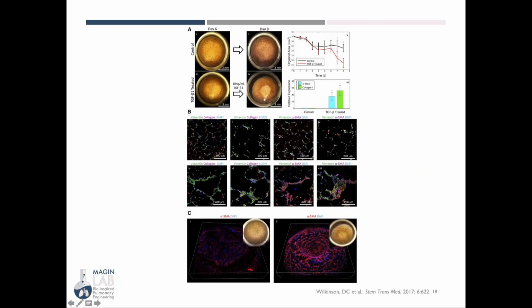So you can see here, you're starting to see the structure of lung tissue. They've stained vimentin, or the fibroblasts, in green here, collagen 1 in that magenta color, and then of course DAPI is blue. And so using these alginate beads, they've created the geometry that we're expecting to see in lung, and they've done this in a 3-dimensional way. They went on to study how these cells can be activated by exposing them to TGF-beta, one of the growth factors that helps induce the fibrosis cascade. And they've seen increases in both alpha smooth muscle actin and collagen 1 when they treat these systems to recreate fibrosis.